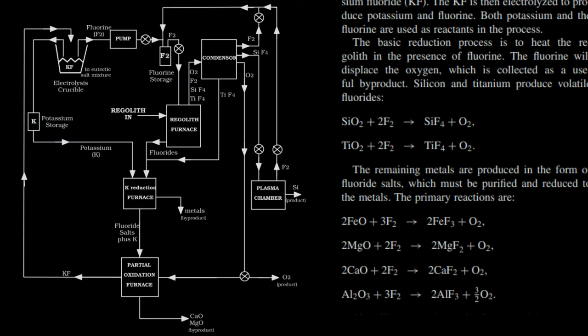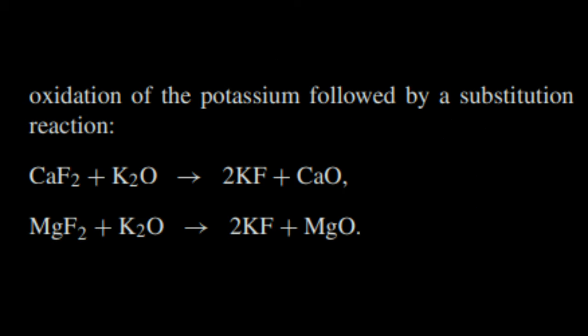After removal of the volatile fluorides and oxygen, the remaining regolith is in the form of fluoride salts. To remove the fluoride and yield pure metals, we reduce these salts with potassium, which will steal the fluorine from the metals, similar to the way calcium steals oxygen. This will leave us with aluminum and iron, which can be removed from the potassium fluoride via melting. The calcium and magnesium fluorides are not reduced by potassium, but can be recovered either by substitution reaction or electrolysis,